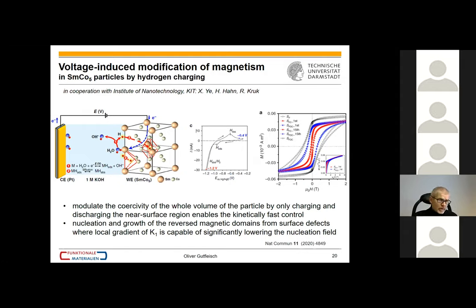So we have here our working electrode, which is samarium cobalt 5, and the counter electrode. And we can then have this hydrogen adsorption mechanism first, reaction one, and then hydrogen absorption into the bulk by interstitial absorption. We have here the voltammogram showing that. And the interesting thing is that we can reversibly manipulate, let's say, coercivity, or first of all, anisotropy. And with this, then coercivity by more than one order of magnitude. And that is interesting because anisotropy should only decrease by about 30% when 1-5 is charged with hydrogen.